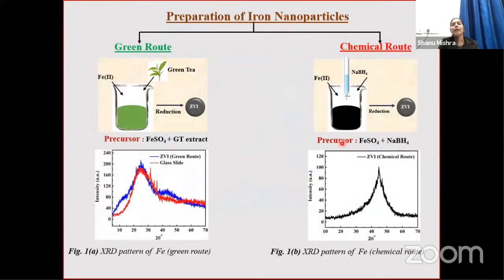As I stated, I have synthesized iron nanoparticles by two different routes. The first one is the green route on the left of the screen, and the right one is the chemical route. For the green route, we chose green tea leaf extract as a natural reducing agent, and the precursor here is iron sulfate. In the chemical route, we chose the typical sodium borohydride solution for reduction of ferrous sulfate.